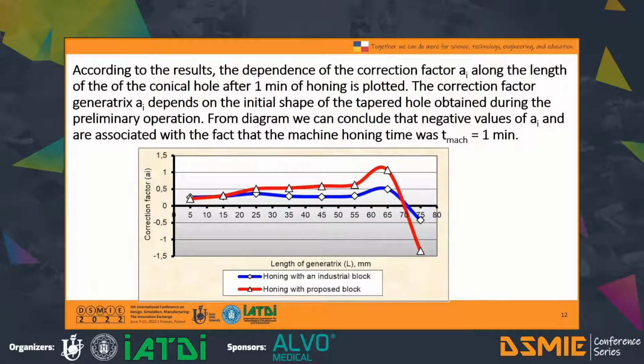According to the results of the given data, the dependence of the correction factor along the length of the generatrix of the conical hole after 1 minute of honing is plotted. The correction factor depends on the initial shape of the tapered hole obtained during the preliminary operation. We can conclude that negative values of the correction factor are associated with the fact that the machine honing time was 1 minute. This time is not enough to correct the errors of the preliminary operation, the maximum values of which took place in the area of the small end of the cone.